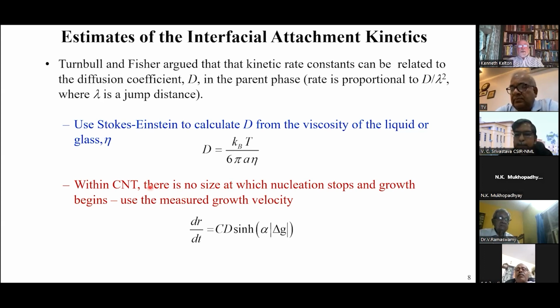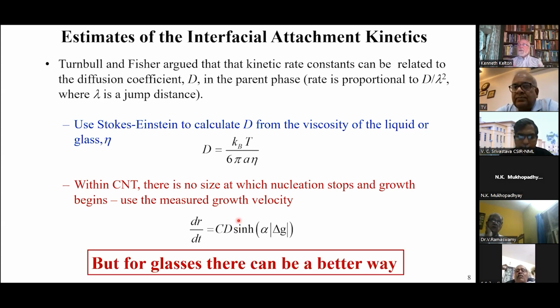Another way is that because in classical nucleation theory, we often talk about nucleation and growth, but there really isn't a cluster size at which nucleation stops and growth begins. It's a continuum. And you can measure then what the growth rate would be from that continuum, and you get an expression like this. So you could measure the growth rate, and from there you could calculate the diffusion coefficient. But for glasses, there's a better way.